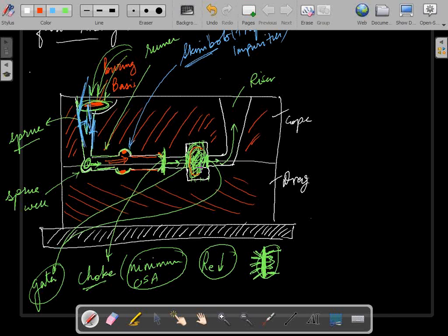So when the volume decreases, you need reinforcement metal to fill up the lost space. That reinforcement metal will be supplied through the riser. This means the riser acts as a reservoir to compensate for solidification shrinkage. This is one of the most important functions of a riser.